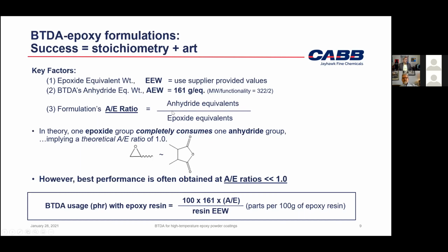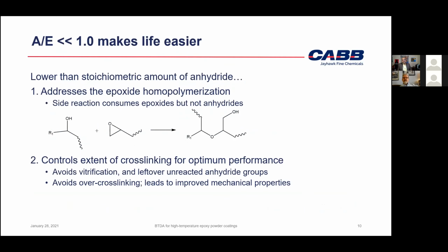And that is the anhydride equivalents divided by the epoxide equivalents. So it's the ratio in the formulation of the anhydride to epoxides. Now, if you look at just the cross-linking reaction, not the homopolymerization, just the cross-linking reaction, you will see that one anhydride group will be equivalent to an epoxide group, and that normally tells you to use a 1-to-1 ratio, an A/E ratio of 1, but you get far better results by going anhydride starved and epoxy excess in these formulations.